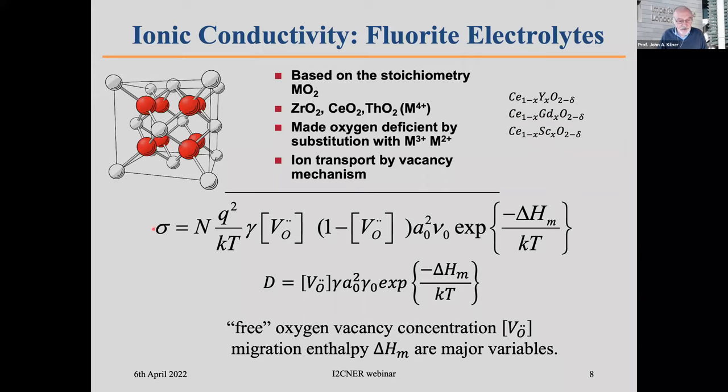So we need really to look at the equation for the conductivity of these materials. This is it. I'm not going to go through all the terms, but really to point out that the two most important terms in here that vary very strongly from oxide to oxide are the oxygen vacancy concentration, which is denoted here, and the migration enthalpy.